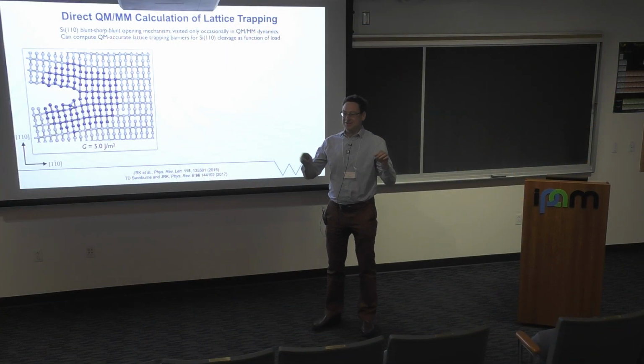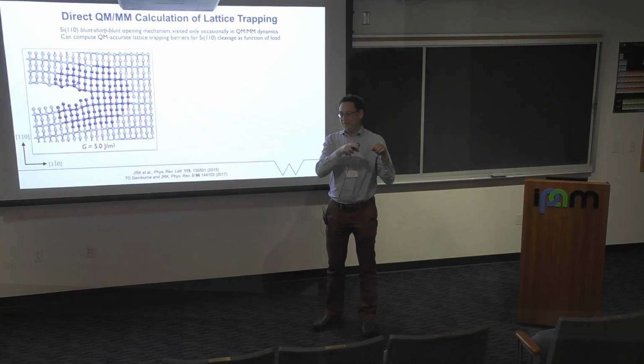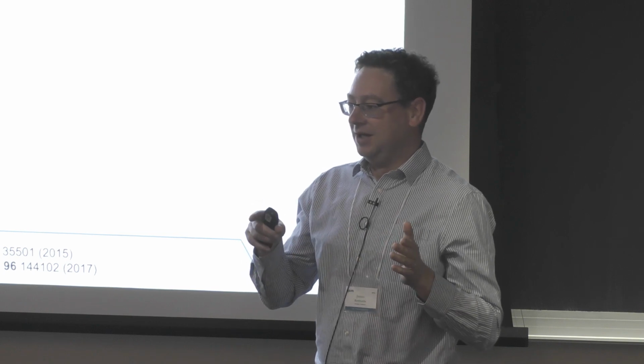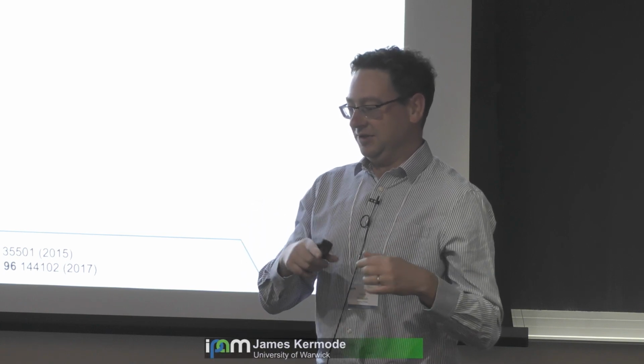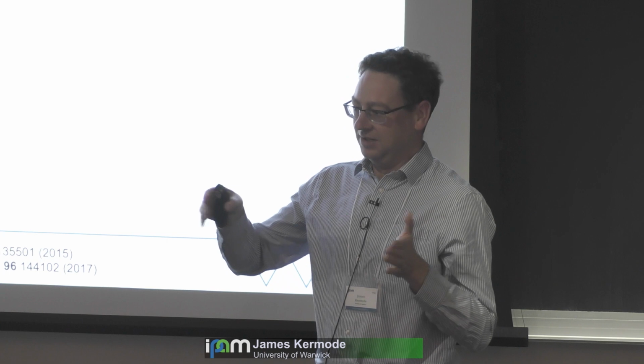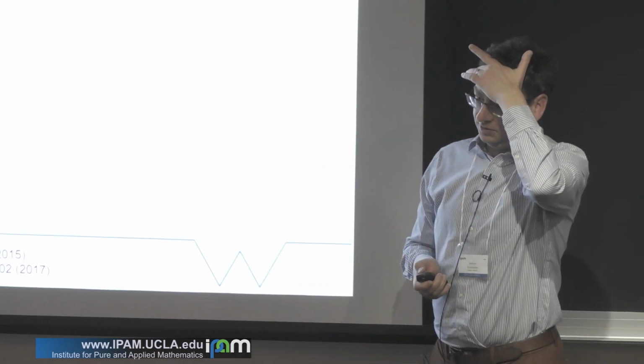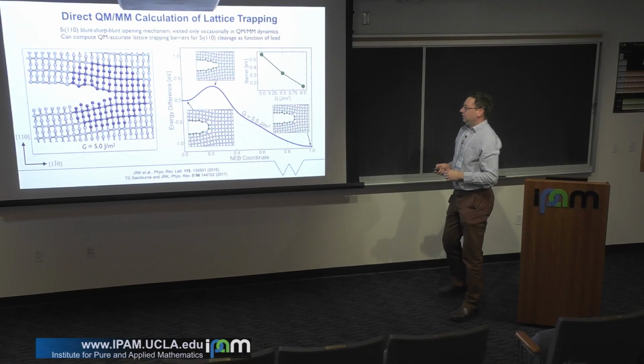But so we have minima at the two ends. We join them with a chain of states. We have springs that connect those images. And then we relax the entire chain with the springs ensuring that the images stay well spaced. And in that way, we relax to the full minimum energy path, including the transition state. So it's quite a well-established method, but maybe not outside of atomistic modeling.